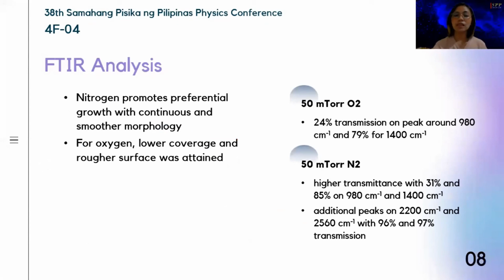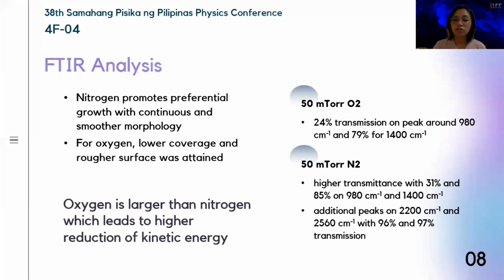Nitrogen as background gas promotes preferential growth with continuous and smoother morphology. For deposited films under oxygen as background gas, lower substrate coverage can be attained. A possible reason for this is that a rougher film with higher porosity was also produced due to the interaction of ablated species and oxygen. Since oxygen is larger than nitrogen, the reduction of kinetic energy through collision was much more effective for oxygen. And this much reduced kinetic energy resulted in sputtering instead of deposition, hence low coverage under oxygen gas.